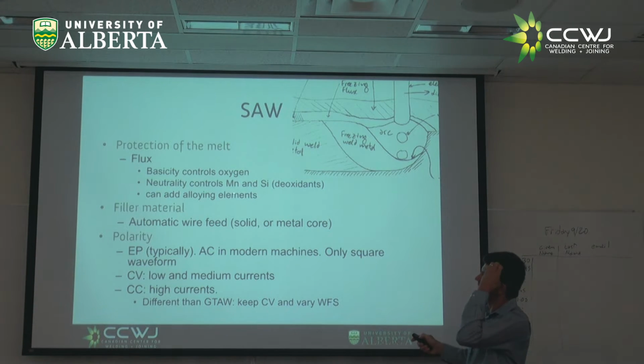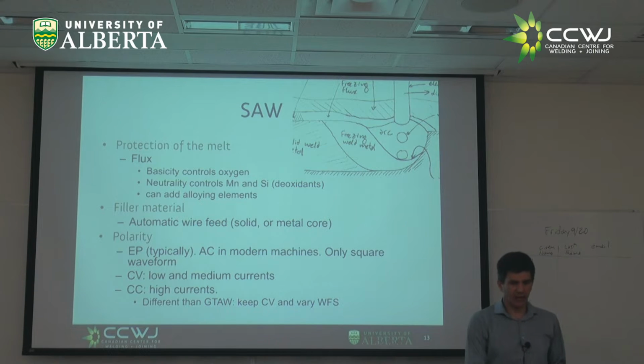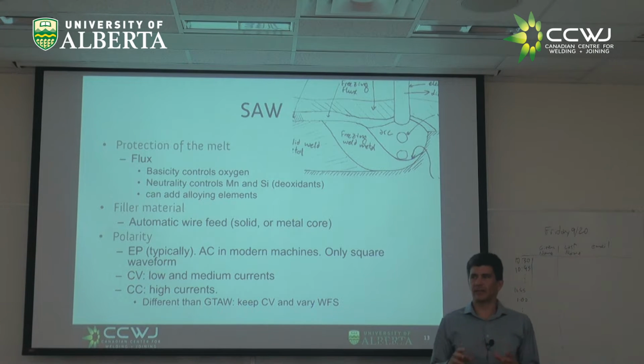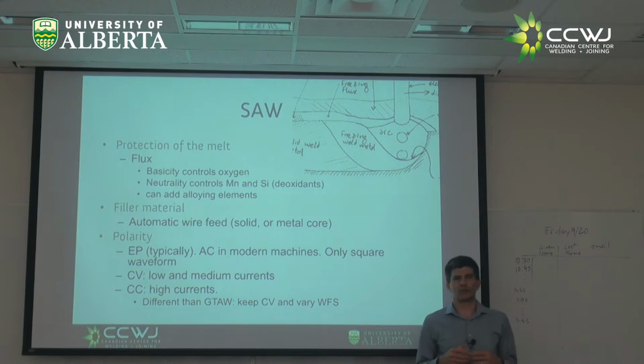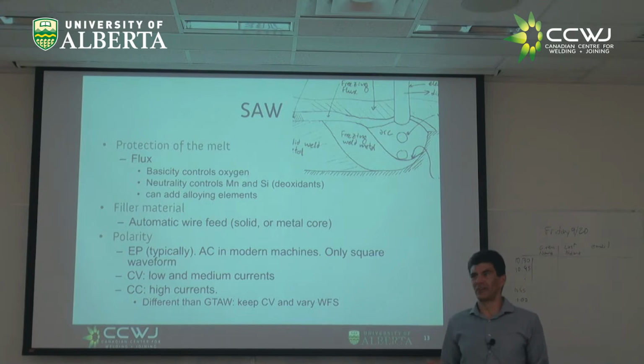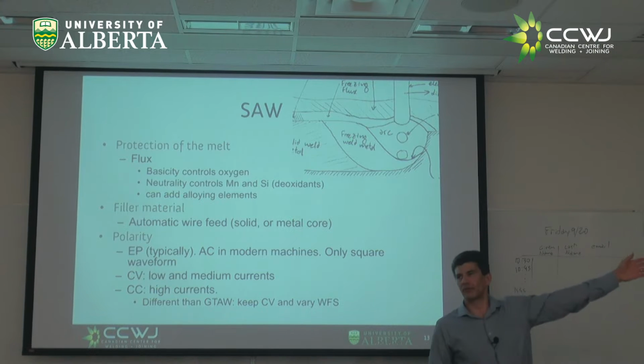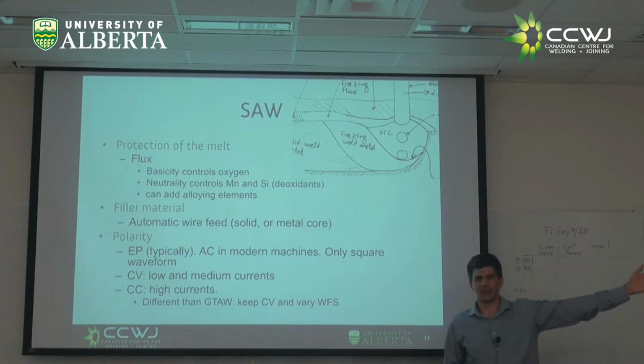Something else is called neutrality. That means if you're going to have more, you're going to change your manganese and silicon content in your alloy. Now, as a preview, manganese and silicon are special because they are very reactive with oxygen. So if you have a plate that is rusty, you can weld on it without problem if you have an alloy that has high manganese and high silicon. Now you might say, why would anybody want to weld on a rusty plate? Well, the answer is everybody wants to weld on a rusty plate because it means you can store it outside and you save money without having a shed, and you can weld it without having to clean it. That saves time and money.